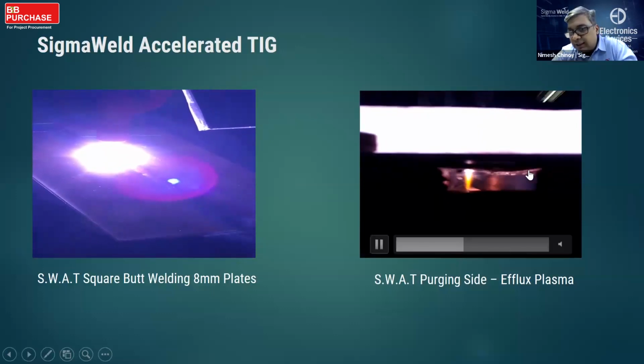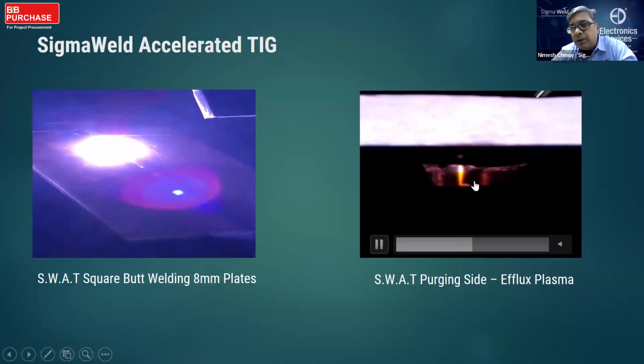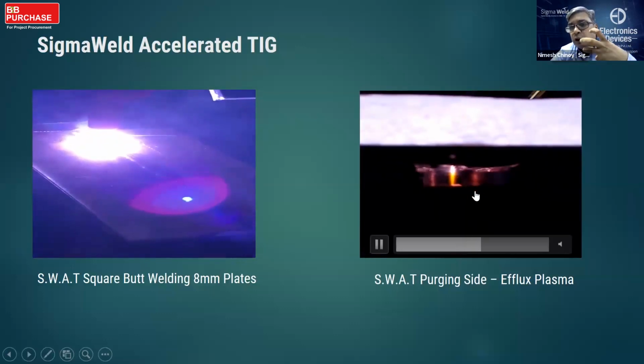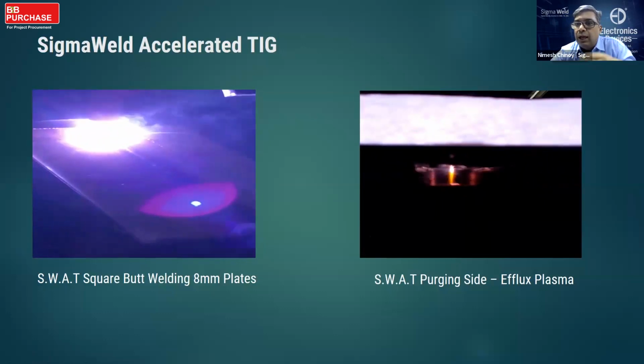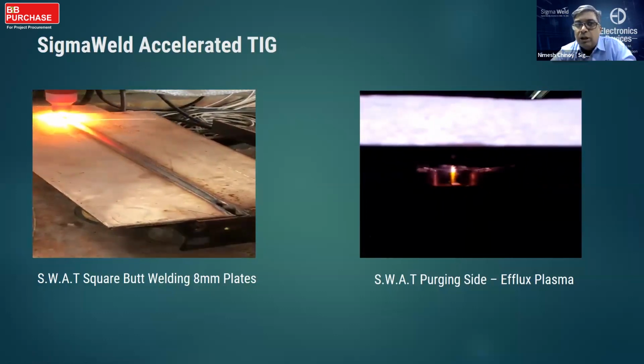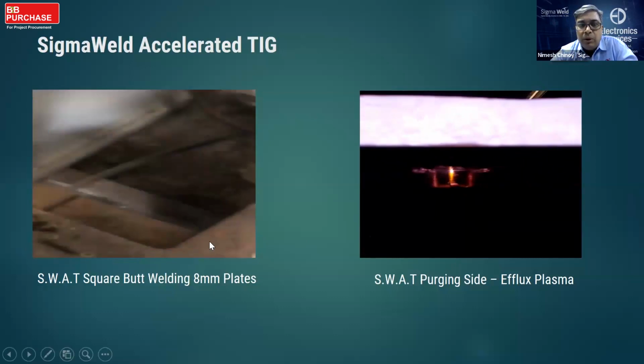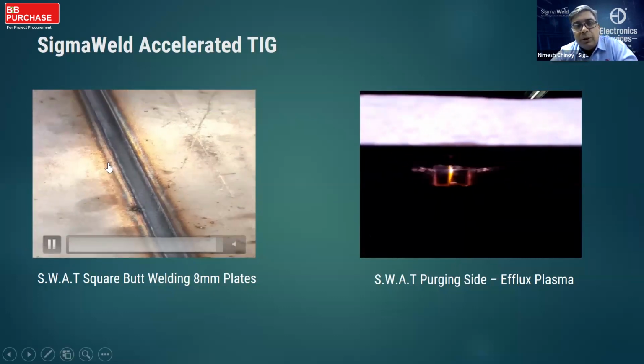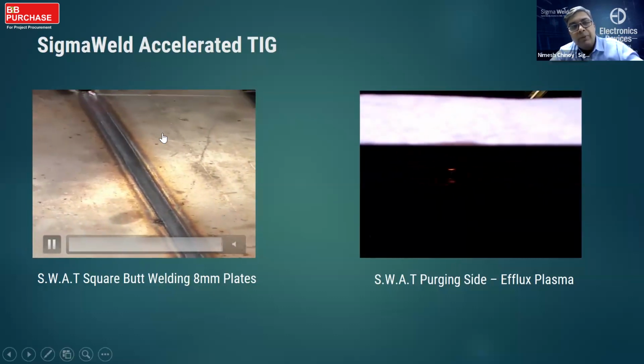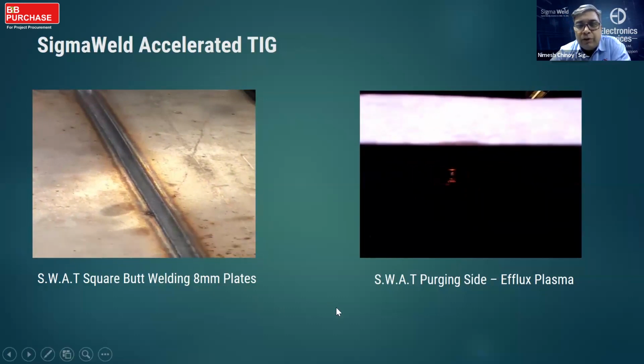On the bottom, on the other side, you are seeing gas exit from the bottom. This is what is an efflux plasma, which shows you that the penetration is full and complete, and it releases all the gases from the bottom side. Once the welding is complete, you can see a full clear penetration joint, and this helps you avoid any kind of confusion at all.